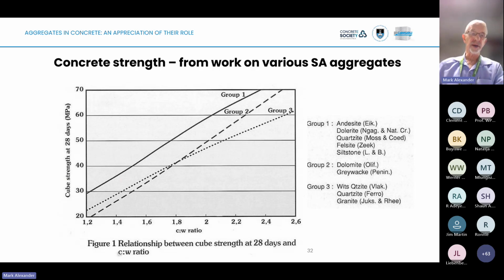Here's an example of some work. Now, I've been working in aggregates since the 1980s, so that goes back a while. This is work we did way back then, where I'm not even sure it's still relevant, but certainly in the aggregates we were working with then, from all over the country, you can see that in this case, we were still working with cement water ratio. So take a cement water ratio of 2, or that becomes 0.5 water cement ratio. And if you look above the 2 here, you can see that the difference in concrete strength could be well below 50 megapascal up to around 60. So maybe 10 to 15 or 10 to 12 megapascal at exactly the same water cement ratio for different aggregates. And this is something which the aggregate people understand, and they make good use of it when they do their marketing.